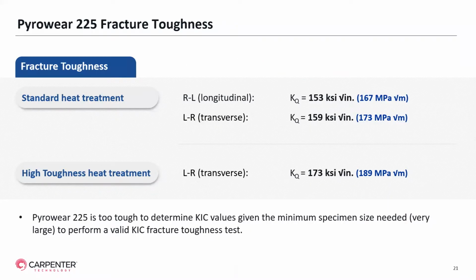We've looked at the fracture toughness of Pyrowear 225. Given our standard heat treatment, we've looked at both longitudinal and transverse orientations. And unfortunately, the material was too tough for us to have generated valid K1C numbers. So I have to report KQ values here. Those KQ values range in the low 150s to the upper 150s, given our standard heat treatment in terms of KSI root inch. Whenever we do that high toughness heat treatment that I made reference to a few slides ago, in the transverse orientation, we're at 173 KSI root inch for the KQ value.